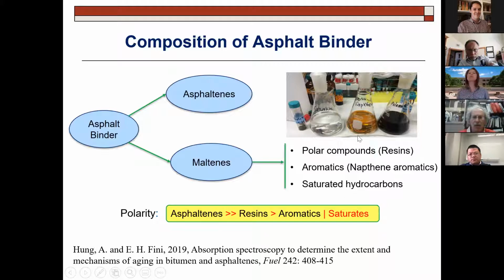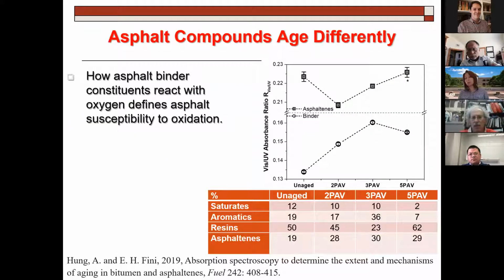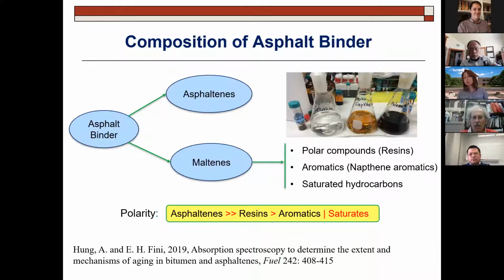And here in the bottle, I should put the picture here from the lab. You can see this little one all the way to the left is asphaltene. Then we have the saturates here, the clear one. We have naphthene aromatics, non-polar, and polar aromatics, the last one. So when they are mixed, they become that same asphalt. When you separate them, they become this. So not every element of it, as you see, is black. Saturate is actually quite clear, or this one is quite yellow. So the whole thing is asphalt.